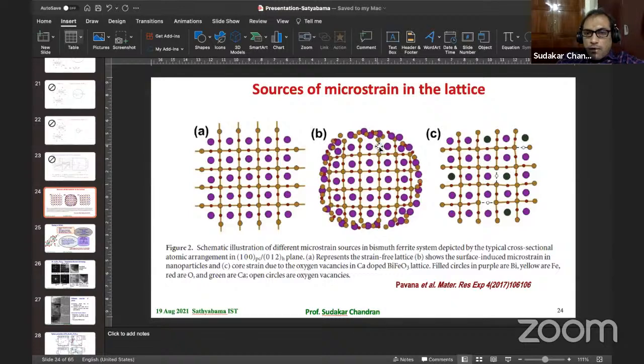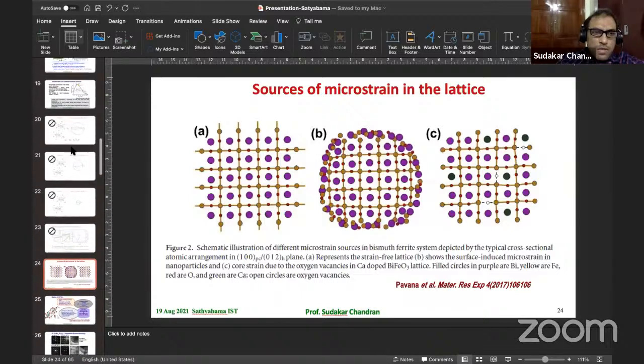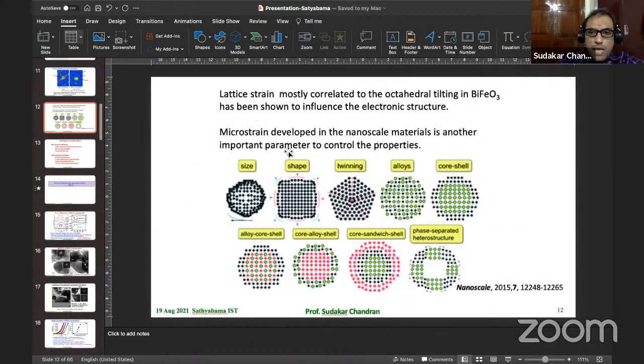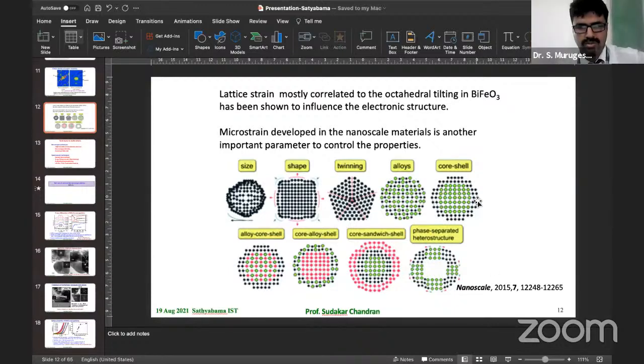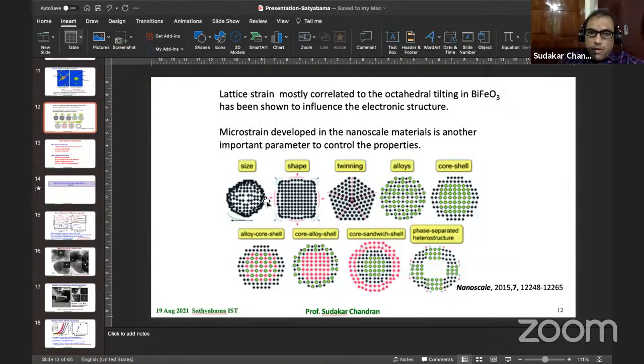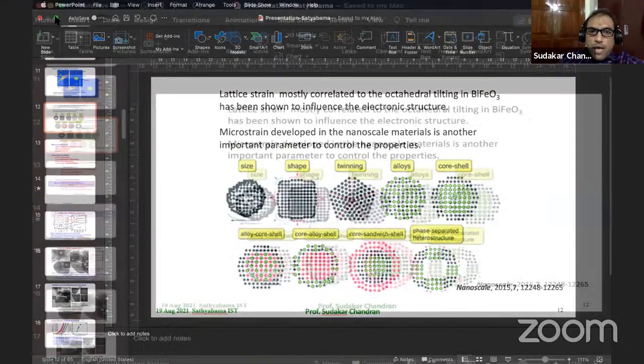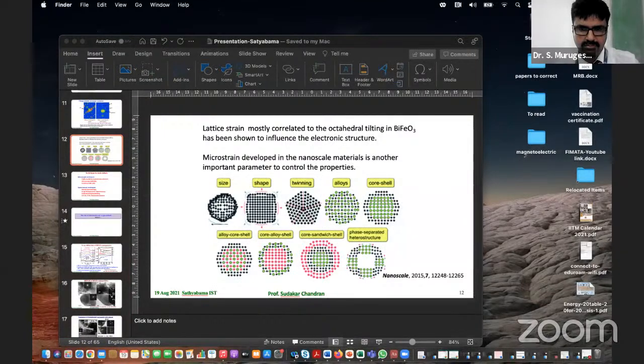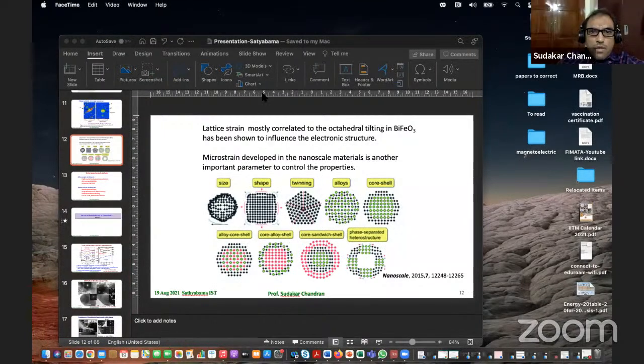which can make the strain permeate to the center of the core, and this is more predominant at nanoparticle size. But in bulk samples, you can do this by introducing oxygen vacancies in the lattice. Anyhow, this is for the oxide cases. If you want to do that in other materials, there are various ways. In fact, this particular manuscript, which is a review article, summarizes various ways one can create microstrain in nanoscale materials. It would certainly affect the electronic structure, and therefore your functional properties would change, and it may be very specific, depending on the different approach you take.